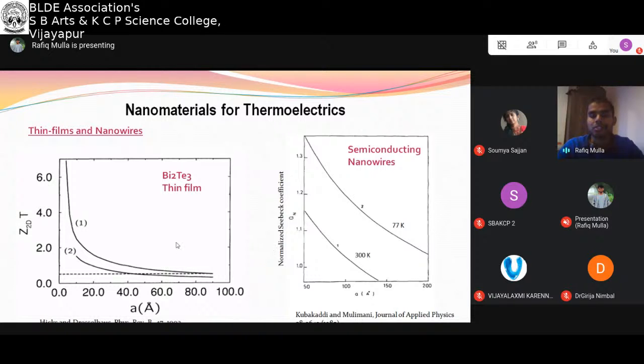So these are some theoretical predictions that researchers reported on thin films and nanowires. You can see this dotted line is bulk. But once it is a thin film, having this kind of thickness, you can see 20 angstrom, 40 angstrom, means 2 nanometer, 4 nanometer. By reducing the thickness of the thin films, you can see how much efficiency they have predicted. So one can reach even a ZT of 6. Presently we are working with ZT of 1 to 2, but by going into very narrow thin films, less than 2 nanometer, one can achieve a very high ZT value.